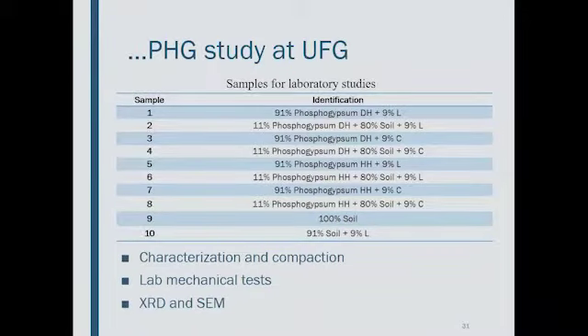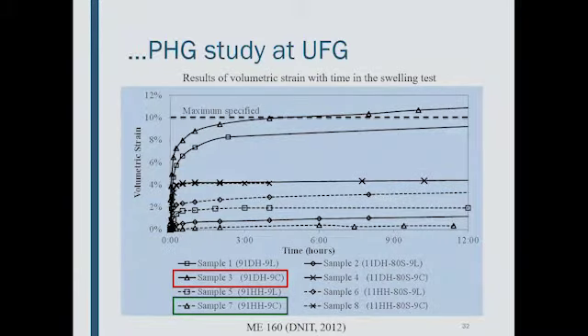We worked with 10 samples, soil mixed with lime, and 8 other mixtures where we changed the type of phosphogypsum, and sometimes we had soil, and in other samples we didn't have soil. Then we performed lab tests: characterization, compaction, mechanical tests, and to complement the results, we performed X-ray diffraction and scanning electron microscope tests. These are results for swelling tests.